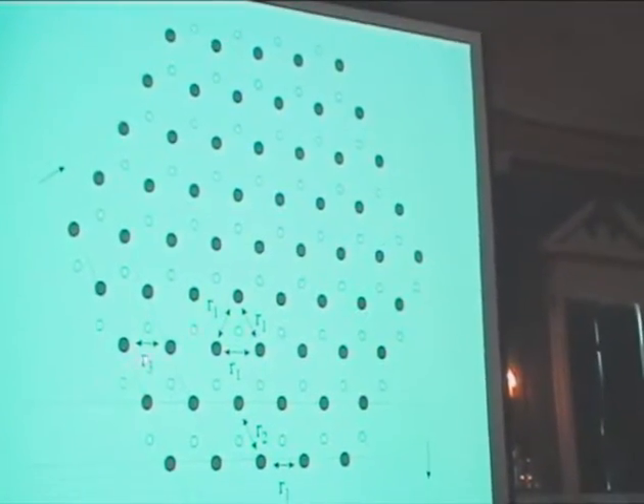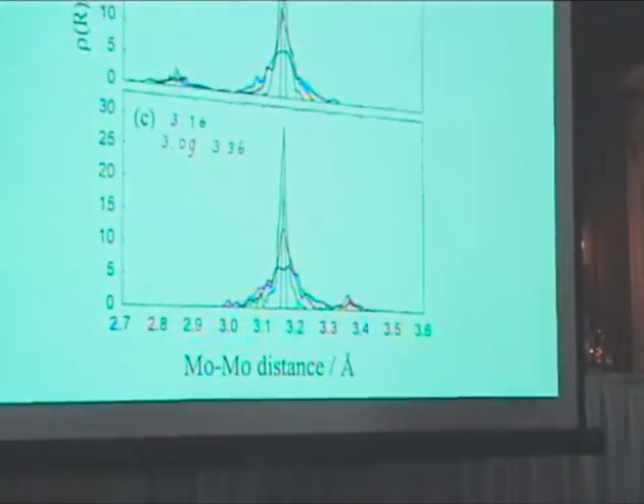However, if you keep the molybdenum to sulfur distance fixed, you can allow the molybdenum distance to vary. So we varied it in a sphere surrounding each molybdenum, and then we randomly put the molybdenum atom there, keeping all the molybdenum sulfur distances constant. So the computer had to do it, because you can start, for instance, at the edge, and make this well, but if you're not careful and you put this in the wrong position, not all of them come out within a certain sphere, like only a deviation of 400ths of an angstrom. And so you have to do it by computing. And in a second model, we allowed the edge to contract only half of the positions, for instance this and here. And in a third model, which I'll show you, we allowed this edge to contract and this edge to expand. So here, I'll show you the three models.